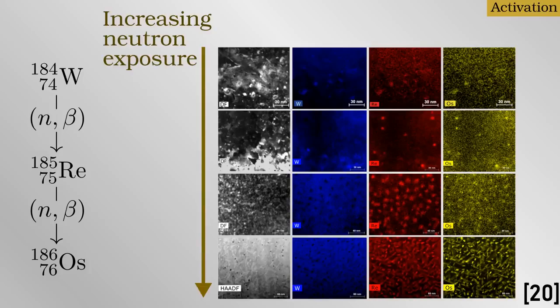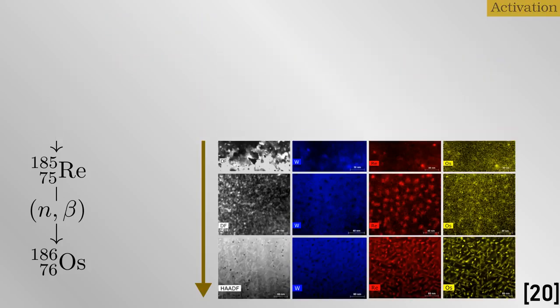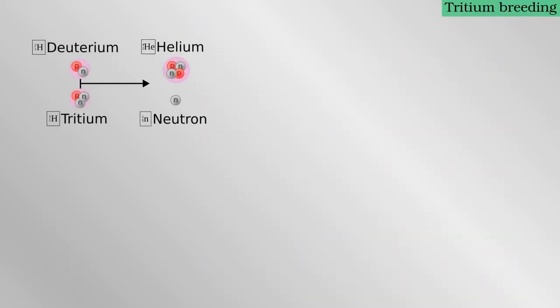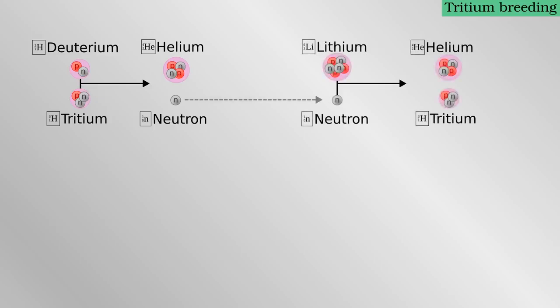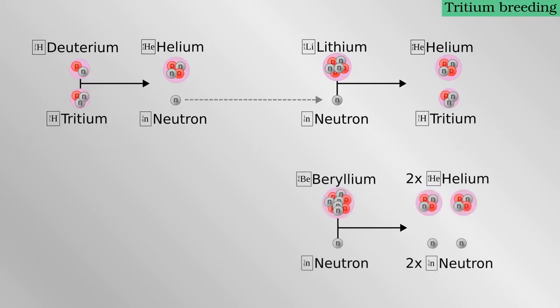Under neutron irradiation, tungsten transmutes to rhenium and osmium. Atoms of these two newly generated metals seem to clump together within the original structure and change the mechanical properties. Tritium does not occur naturally and must be generated or bred within a future power plant. Fortunately, lithium-6 can be activated by neutrons to produce tritium and a little extra energy. One tritium nucleus undergoes a fusion reaction to produce one neutron, which in turn produces one tritium again. The cycle works assuming perfect efficiency, but as we have seen, some neutrons will be absorbed elsewhere, and some tritium will be lost or decay away radioactively. Fortunately, beryllium can release 2 neutrons when struck by a single one. Therefore, for some of the original neutrons, the tritium production is doubled and the losses can be made good.